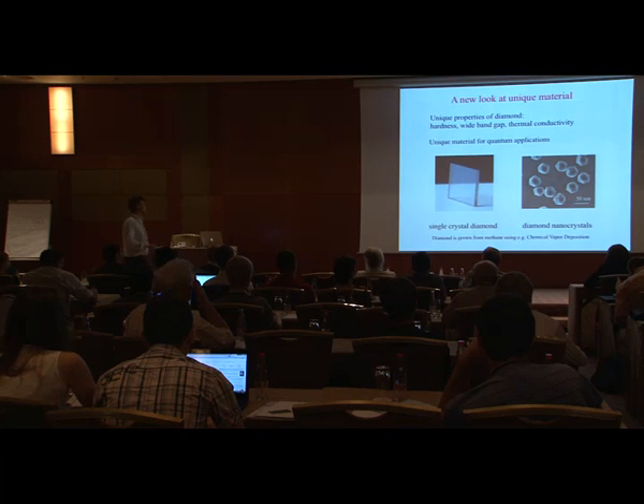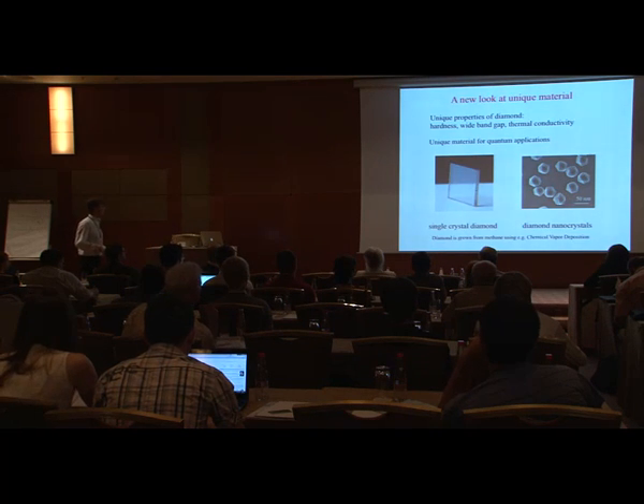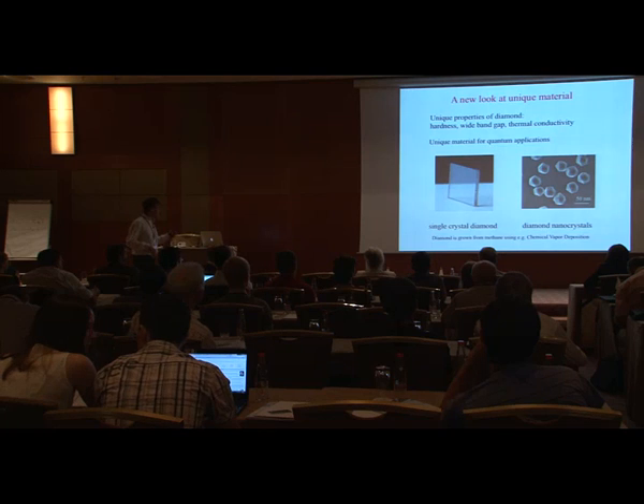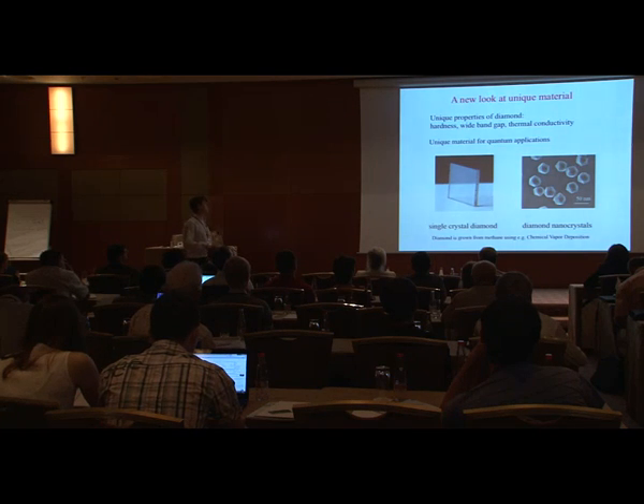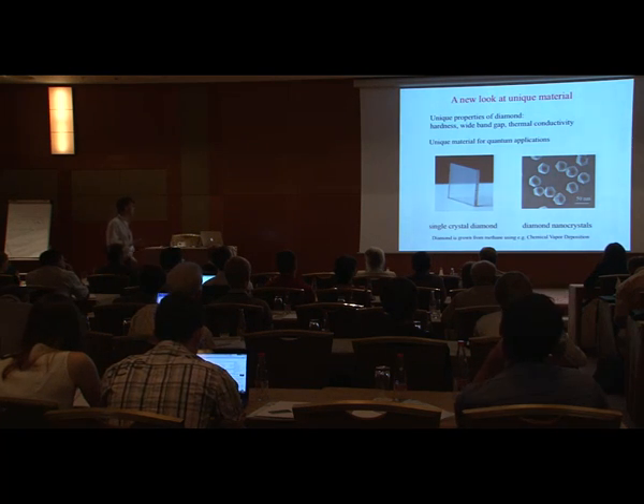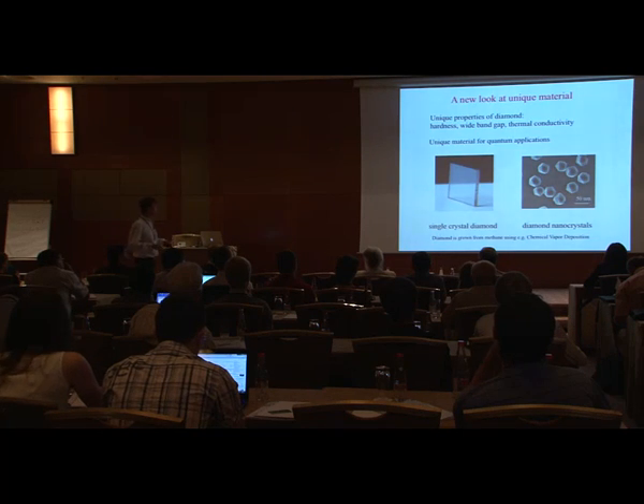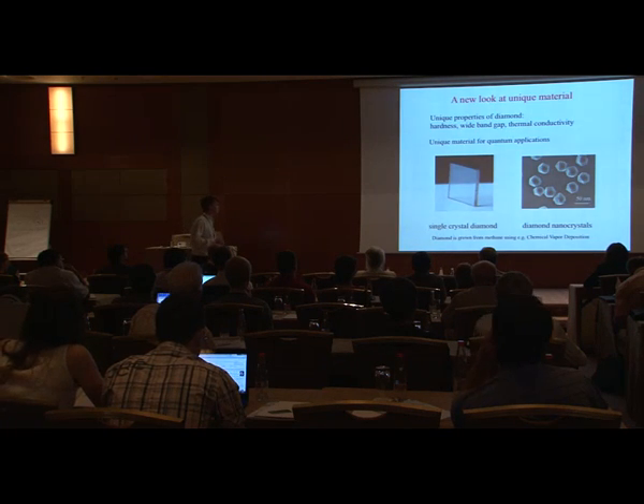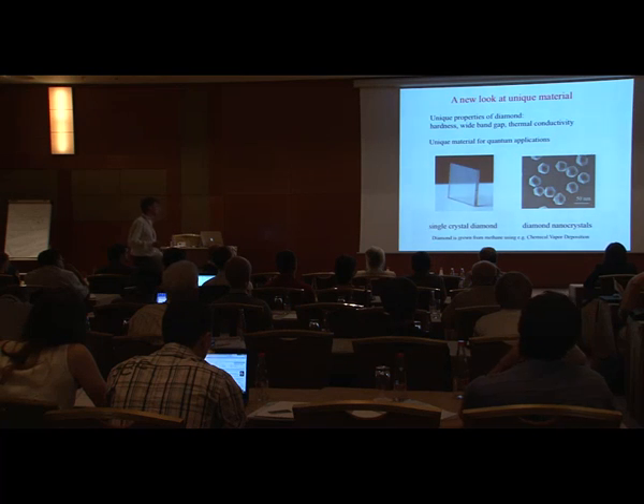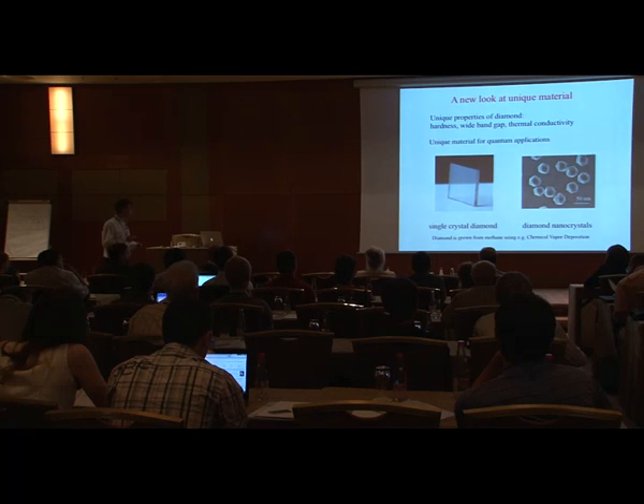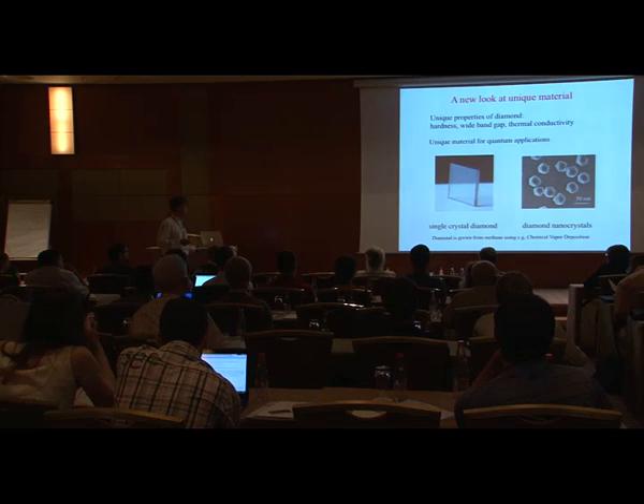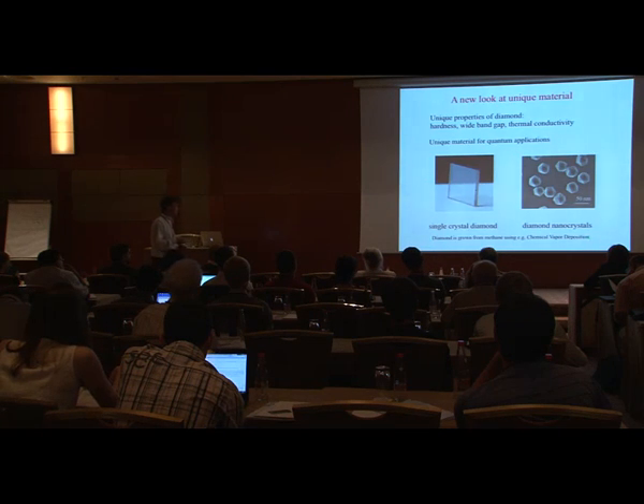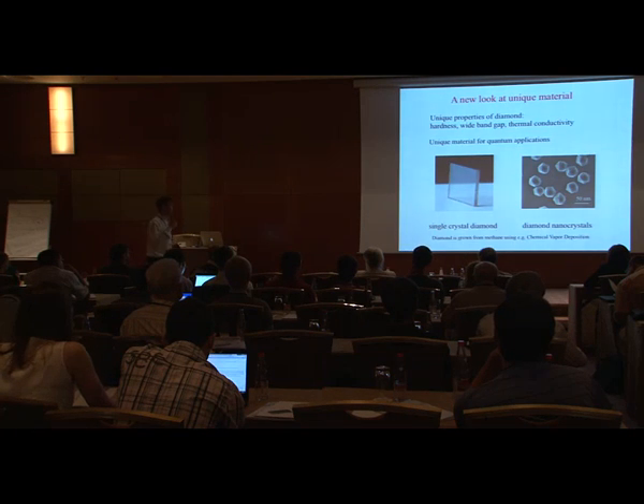So all these developments are based on advances in modern materials. In particular, diamond is known to be a unique material for its hardness and thermal conductivity. It turns out that these properties make it quite unique for quantum applications. Most remarkably, it is now possible to grow diamonds from a gas, from methane, using, for example, chemical vapor deposition. And in the growth process, one can really control its properties, its composition, its purity, one can even shape the diamond structure the way you want.